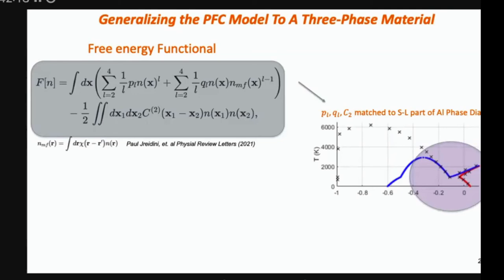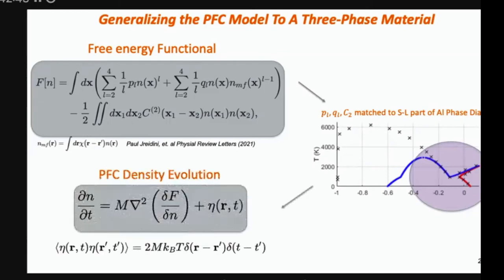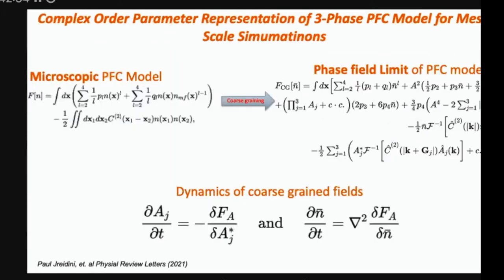I'll rush past this a bit and just show this model is the model Paul recently came up with, where the first term is a polynomial expansion. N is the reduced density of the system. That's your order parameter. And at the bottom C2, that's where you put the non-local effects. So if you just want a simple model A, it would be a grad square. But if you want to have higher order gradients, you can capture order parameters that solidify in either constant states, liquid or periodic states, solid.